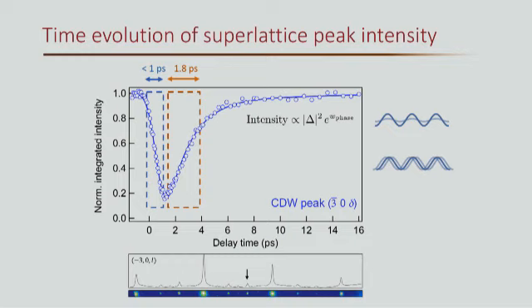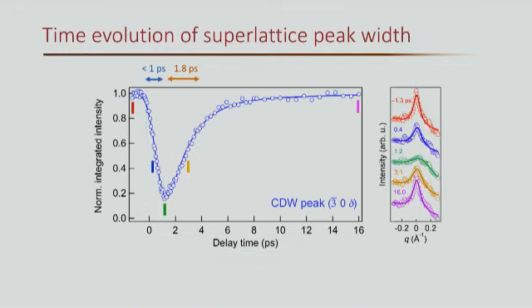So pictorially, what happens is that as you pump with the laser, in terms of lattice movement, the distortion gets suppressed, and at the same time there are a lot of phase fluctuations. We can dig deeper by looking at the profile of the peak at representative time points. I plot the raw data of this superlattice peak at these color bar positions. You can see it gets suppressed around 1.2 picoseconds, and then gets enhanced again. If you look at the graph on the right-hand side more carefully, you can also see a broadening of the peak as you suppress its intensity.